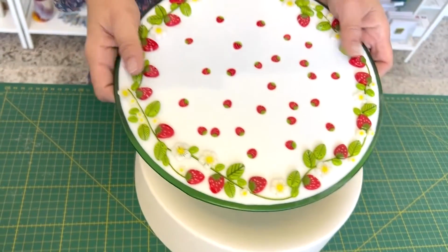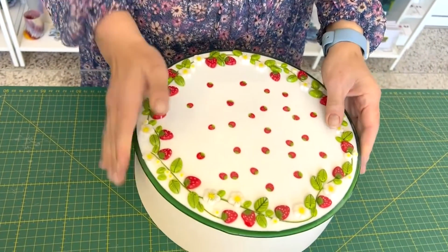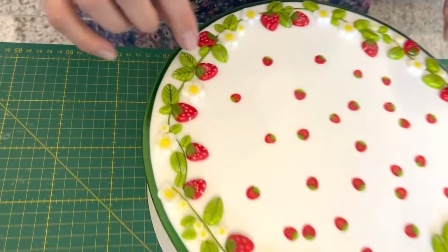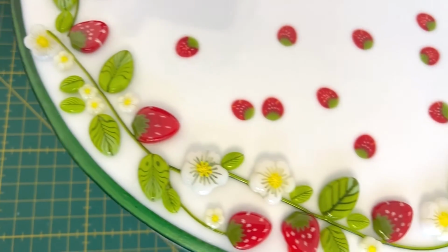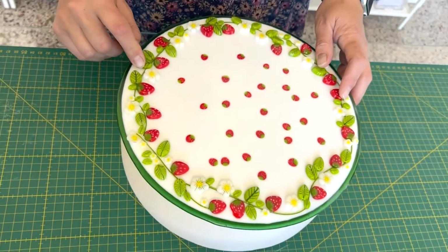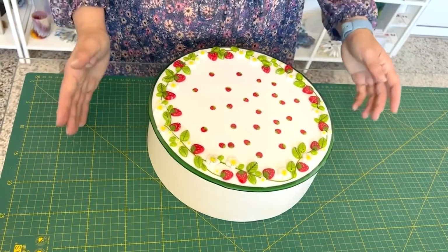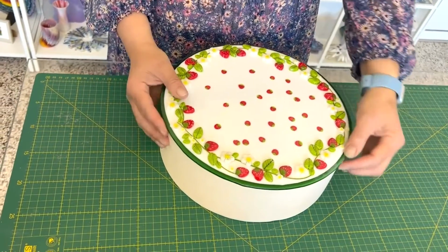So here this is out of the kiln. I'm loving how it's looking. It's going to go in for a slump now. It's going to be very, very low and slow. It's got these different layers, thicknesses. So I'm going to do 70 degrees an hour, take it up to the slumping temperature, and then I'm going to do a 6-hour anneal on this, guys. It'll be in the kiln for a couple of days. I'd rather be safe than sorry and take it slow and end up with a beautiful bowl than take it too quickly and it be cracked.